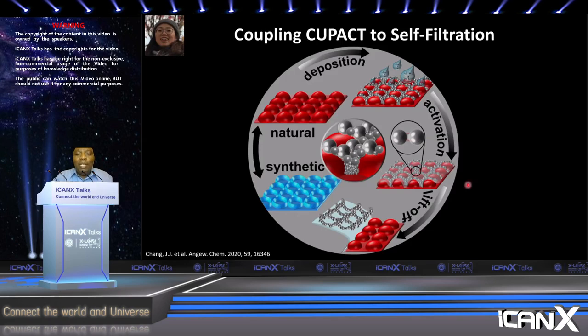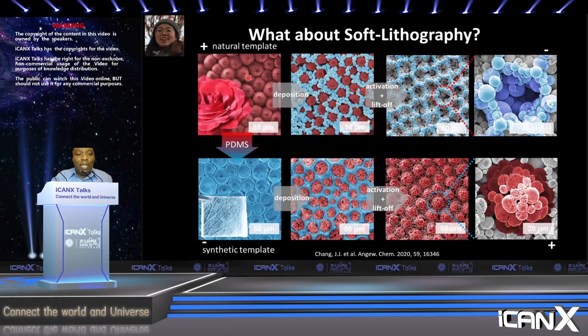But now that we can do that, what else can we do with this? What if we couple the self-filtration and the sintering to make structures that we can lift off? Can we start making mimics of, for example, the rose flower? If we take a rose flower and put particles and sinter them, we lift them up. If we start with the opposite, where we take the rose flower but first make an elastomeric mold and then repeat the same process, we will get a replica of the rose. If we use the rose as our template, we get a negative replica of the rose flower. Based on that, we did exactly that: we took a rose petal and filled the particles all the way to the top. You can see that after we solidify this, we can lift them up and get very nice, well-networked structures here.